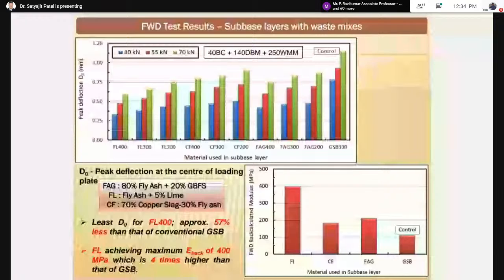So this is the result from the field test, which gives a more accurate result of the actual field condition. You can see here the D0 value is approximately 57% less than that of conventional GSB. Then the elastic modulus of 400 MPa is 4 times higher than that of GSB material. So this cemented material has a very high stiffness, or elastic modulus, compared to the conventional one. It gives low deflection at the top compared to the conventional one, also with cost saving.